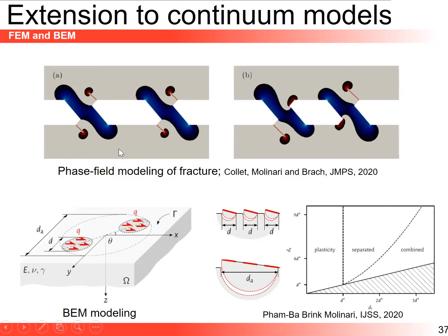So this is just an illustration from this paper, one out of many, to show that in fact, when two junctions are nearby, here you see this image, at those high tensile stress regions, at the inner cracks, the cracks cannot propagate because the outer crack propagates faster. So she recovered those mechanisms, and again, that opens up a large field.